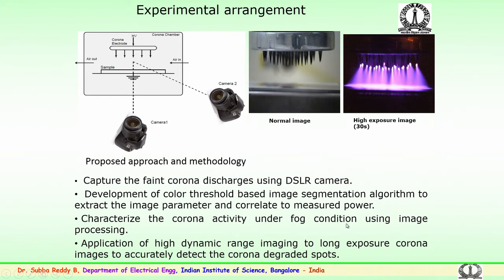processing techniques. Further, application of high dynamic range imaging was also attempted, particularly on long exposure corona images, and it was seen whether this could accurately help in detecting the corona degraded spots. So, the effort has been made towards this, and some encouraging results have also been obtained. This will help as an alternate tool to estimate the surface degradation or surface properties in field conditions.